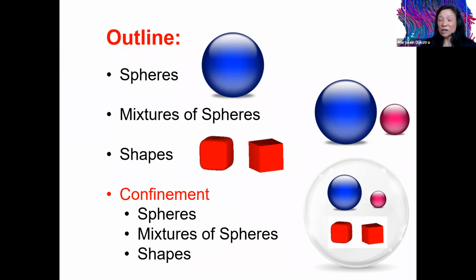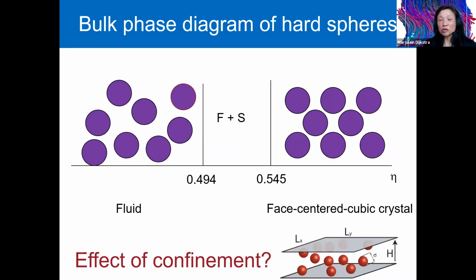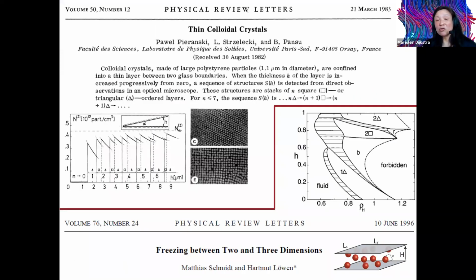We can also increase the diversity of crystal structures by using just confinement. And for instance, if we start with a face-centered cubic crystal of spheres, one can also ask the question what happens if you confine these spheres into a planar slit. So if the slit consists of two planar hard walls and you confine the spheres in between. And this question was already addressed by Pieranski and Pansu, who did experiments on these colloidal spheres in between two glass platelets. And the angle between these glass platelets is given by this angle, and by just using this angle, they were able to probe all possible plate separations at once.